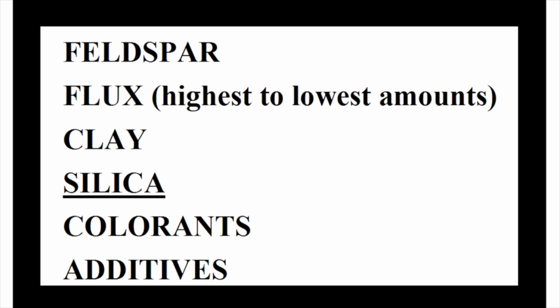Glaze recipes should always be listed in this order to better understand and evaluate the glaze: first, feldspar; second, the flux, highest to lowest amounts; third, clay; and fourth, silica. That should sum up to 100%. Then list the colorants, and lastly, the additives.